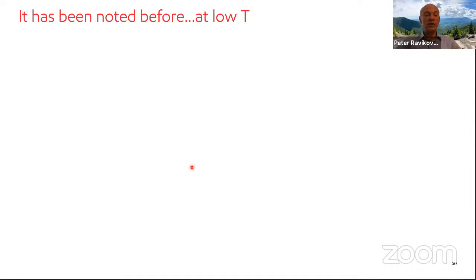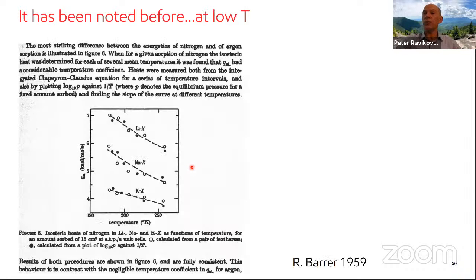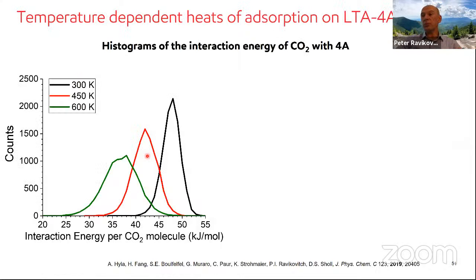We started looking in the literature, and yeah, sure enough, R. Barrer reported temperature dependence for polar molecules adsorption in cationic zeolite, particularly in lithium X zeolite. At very low temperature, though, that was observed at something like around 200 K. So what's going on? Molecular simulations give you a way to look at what's going on. What you can do is plot the histogram of interaction energies at different temperatures. And you can clearly see that the interaction energies decrease as you increase the temperature.